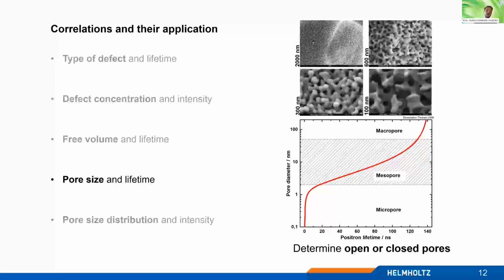What else? If you increase the voids or pores even more, then you reach the size of nanopores, which are important for catalysts or carbon capturing or wastewater treatment. And what we can see here is that the positron lifetime is correlated with the pore diameter. And the model we use here is the extended Tao-Eldrup model, which is well known for more than 20 years now. So this is a good tool to also investigate these kinds of pores.